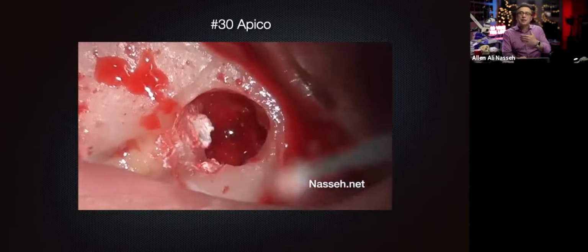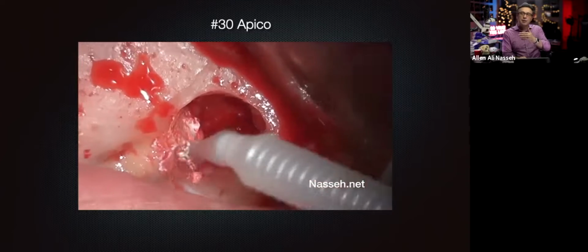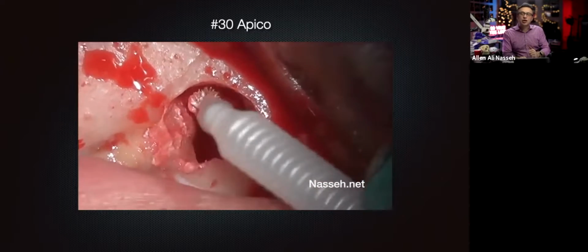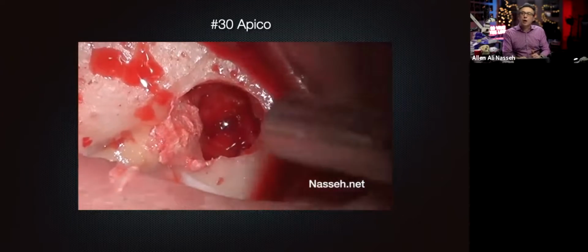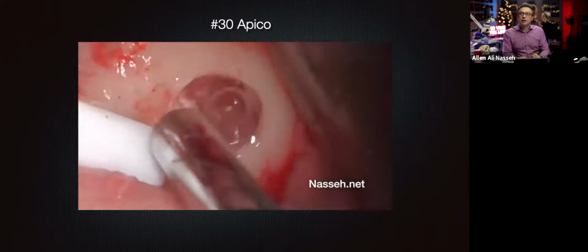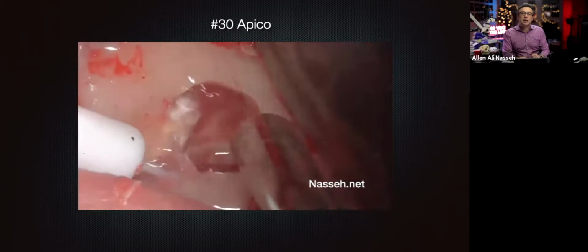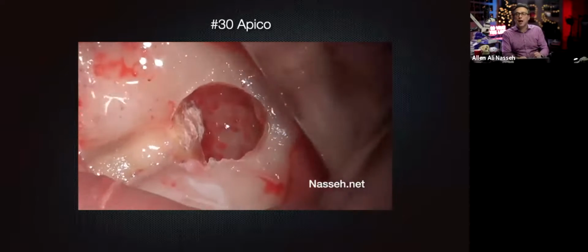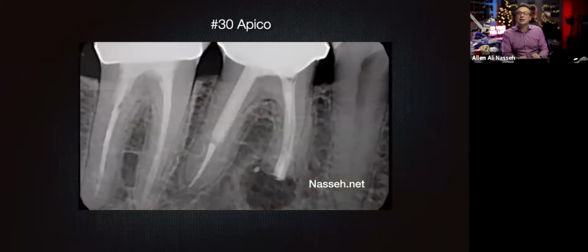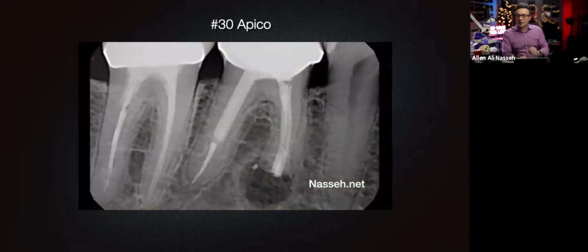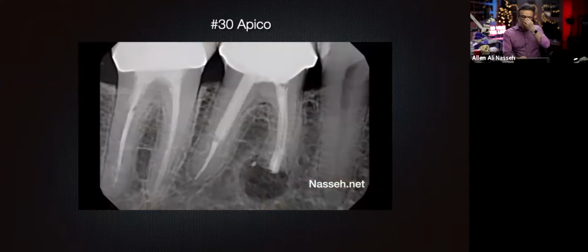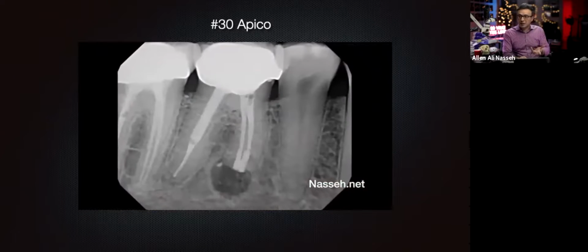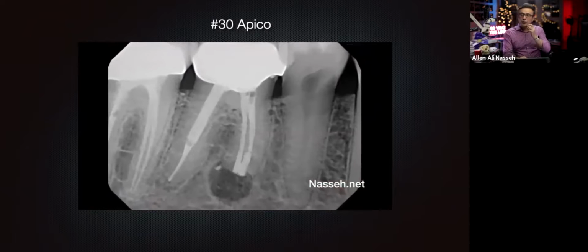And then what happens is that I come back, add a little water, and then I use a micro brush to remove the flash, and then use water to wash out the dislodged flash here. And you can see this is not something we could have done with MTA before. It would wash the whole thing out, but the putty fast set does not wash out that easily. And here it is. And even if you have a little tiny flash, you can see here, it's not a big deal. And here's a little angled X-ray showing each one.